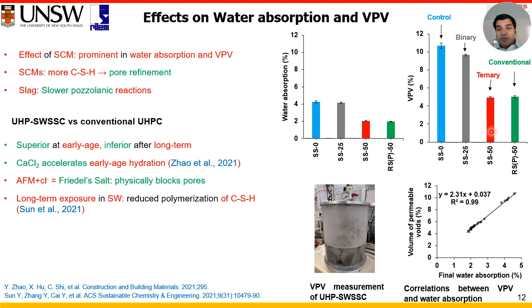When marine UHPC was compared to conventional UHPC, we found that marine UHPC generated superior transport properties at earlier age, however slightly inferior after long term, which is because the calcium chloride present in seawater can accelerate the early age hydration, and after long term exposure in seawater, it can reduce the polymerization of CSH and thereby degrade the transport properties. Also, the AFm phases within the concrete can bind with the free chloride and form Friedel's salt, which can physically block the pores, which we will discuss in detail later.